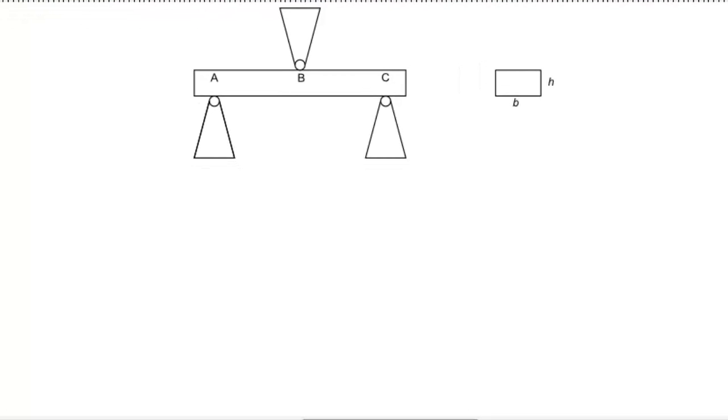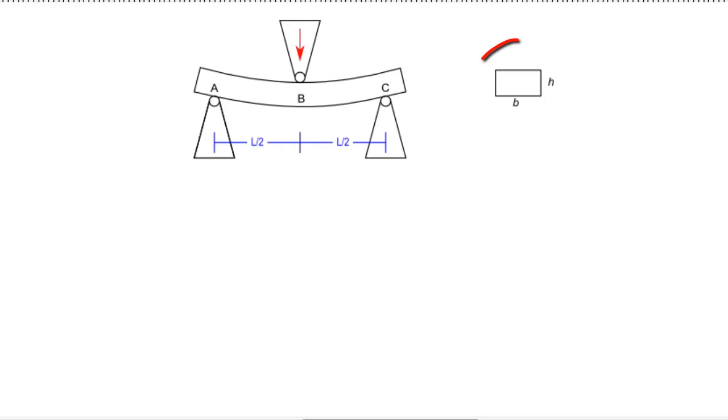Three-point bending tests are commonly used to assess the mechanical properties of brittle materials. It can prove very difficult to test these materials with a standard tensile test, while three-point bending specimens are relatively easy to prepare, test, and analyze. Three-point bending tests are usually conducted on rectangular beams. These beams are placed on two roller supports, and the load is applied via a third roller, typically mounted halfway between the supports.